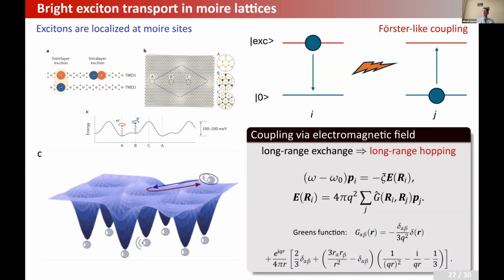you can create an effective superlattice potential for charge carriers and for excitons. I will not go into any theoretical details about it. This potential is, strictly speaking, not periodic. There could be a disorder. And in principle, this potential is quite deep. The depth, at least for some TMD-based materials, is on the order of tens or hundreds of milli-electron volts. That is why excitons can be localized in this potential minimum.